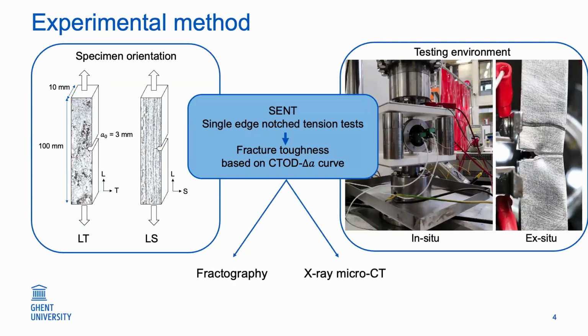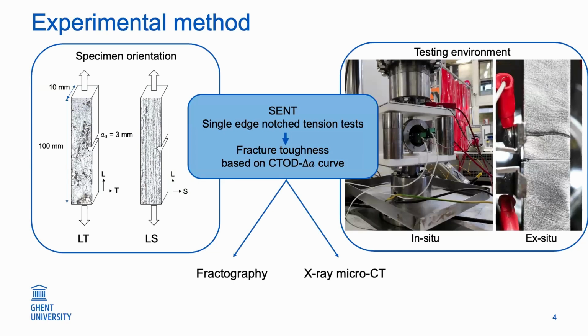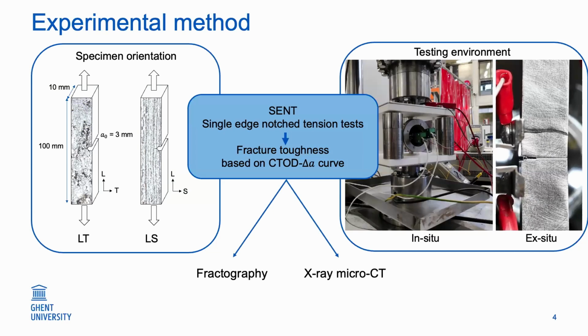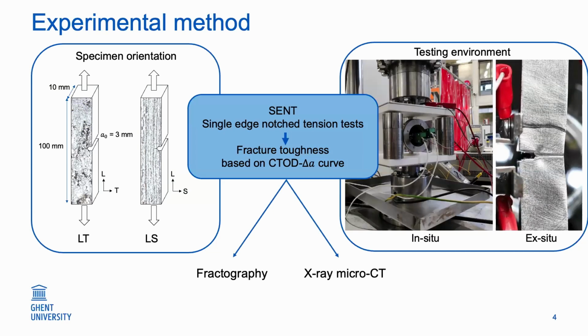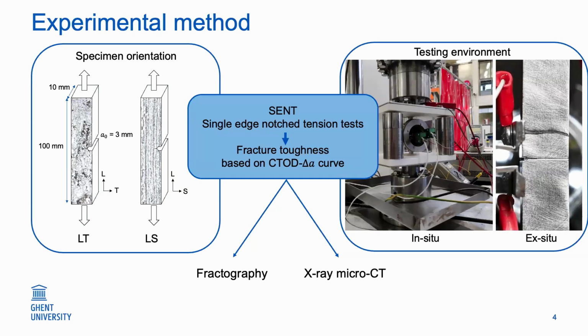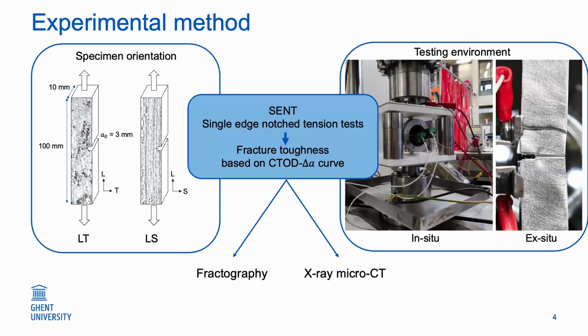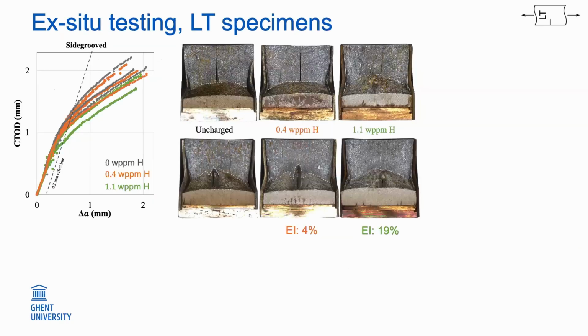And then finally, I will be evaluating the effect of hydrogen using two methods, mainly, which is just fractography, and then also X-ray micro-CT scanning to take a look in the volume, to look at voids. I will be starting with the LT specimens because I think they give a good overview of the three main spheres of influence of hydrogen in these types of specimens that could be identified.